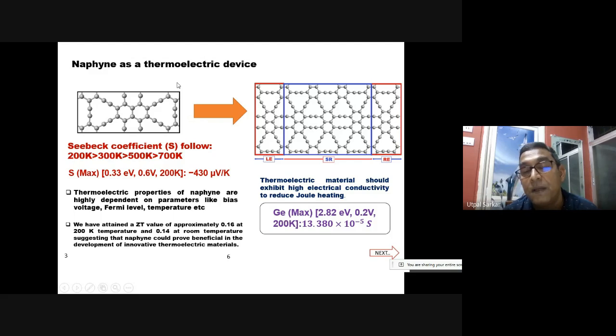Now, some other source of calculations is a thermoelectric device. You see, this is naphyne structure, and we have calculated the Seebeck coefficients, how this Seebeck coefficient changes with respect to temperature, and that you can also calculate here. So here is the device. This is the left electrode. This is the right electrode of this naphyne, and it is the scattering region. So one end is basically hot, another end is cold, and if hot and cold ends are connected, then it will develop some voltage. So you will get some Seebeck coefficient.